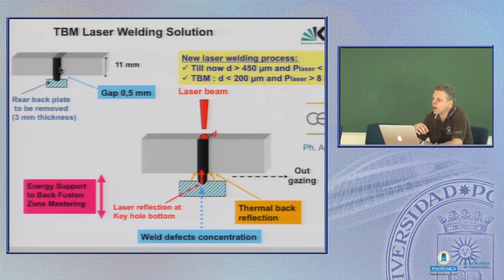Now with beam welding, the problem is that there is a pressure along the beam, and this, I have pictures later on, usually presses the melt down through the weld line. That's why they've used here a substructure beneath the weld which reflects the heat and keeps the melt within both parts.